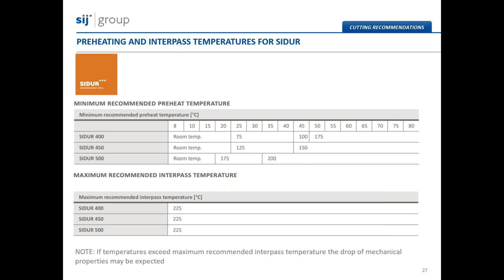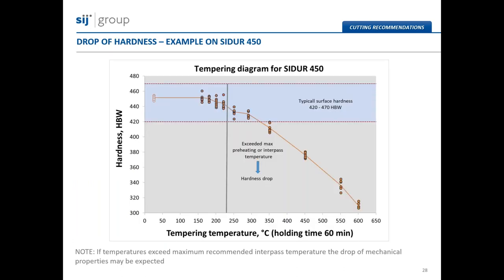For all SIDUR grades, the maximum temperature of preheating should not exceed 225 degrees C. As it was explained before for SIMAXX steel, the drop of mechanical properties can also be expected for SIDUR grades. I will show you just one example. On this diagram, we can see the effect of tempering where the study was done on SIDUR 450 grade.